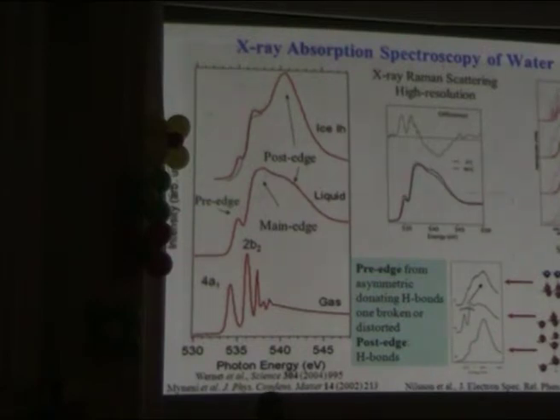Now, what we did was to do a lot of MD simulations of water. We took out different structures and calculated the X-ray absorption spectra. And this is what we find. If we take the structure of ice, we have a good representation. If we look at the liquid simulations and take out molecules that have 4 hydrogen bonds, we get something that looks like ice. If we break an accepted hydrogen bond on the backside of the molecule, it still looks like ice. But if we break one of the donated hydrogen bonds, making the hydrogen bonding asymmetric, then we lose intensity here, we gain it at the pre-edge, we gain at the main edge. So this is a theoretical prediction.